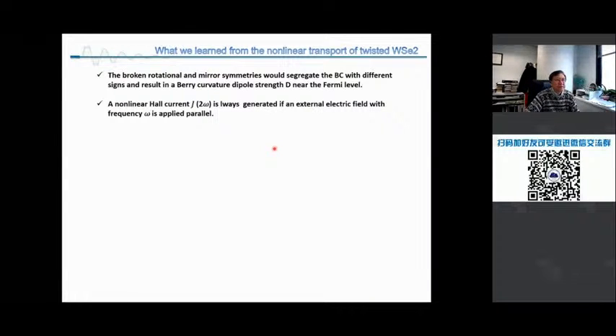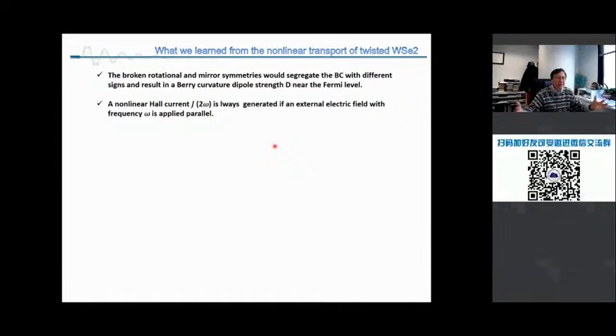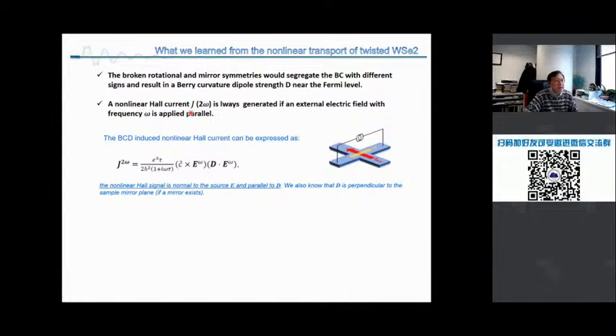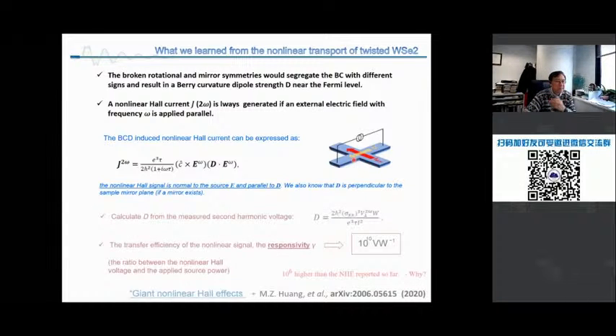The broken rotational symmetry and mirror symmetry will separate the Berry curvature with different signs, resulting in this so-called Berry curvature dipole near the Fermi level. That is different from uniform materials, right? In uniform materials, you do not have this extra thing called the Berry curvature dipole. That's the region where you detect the 2 omega, the second harmonic frequency voltage across the sample, perpendicular to the electric field. So the device is nice, and you simply inject one frequency and detect double frequency. The nonlinear Hall signal is normal to the source, but parallel to the dipole positions.